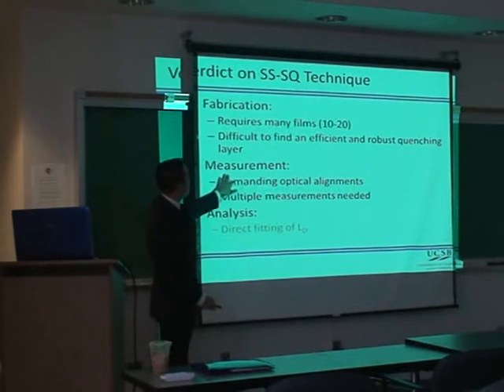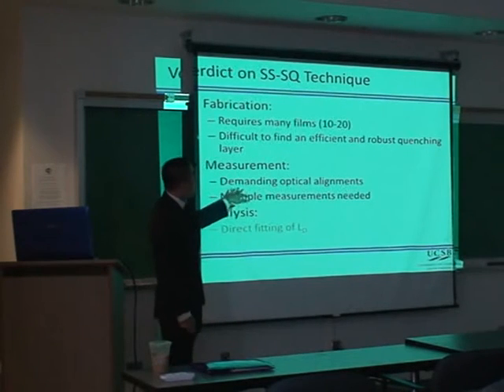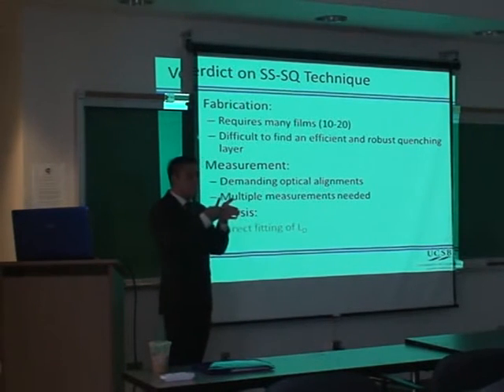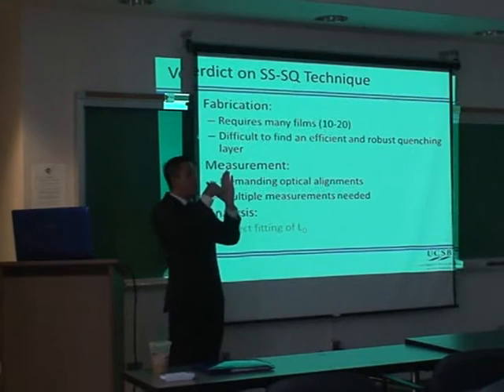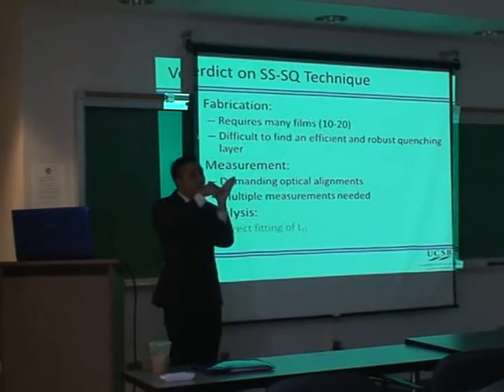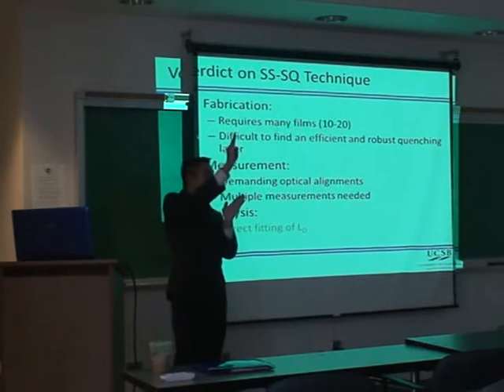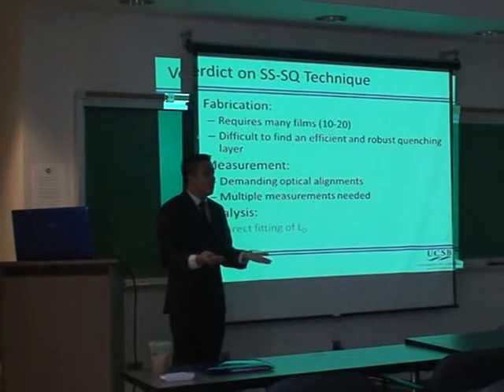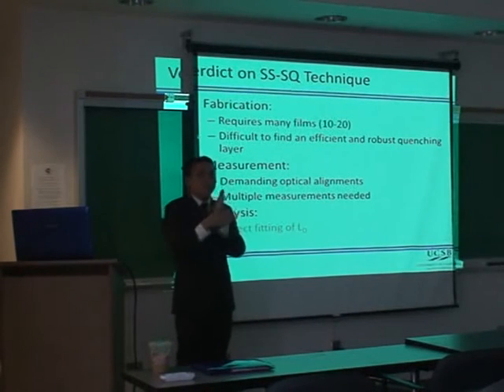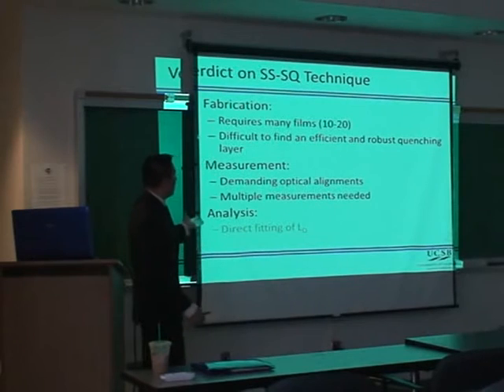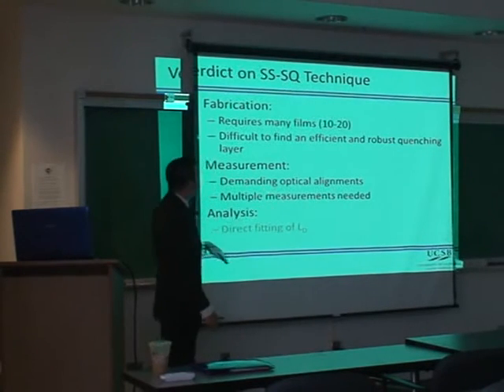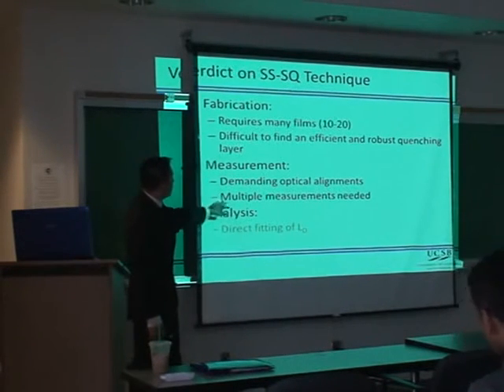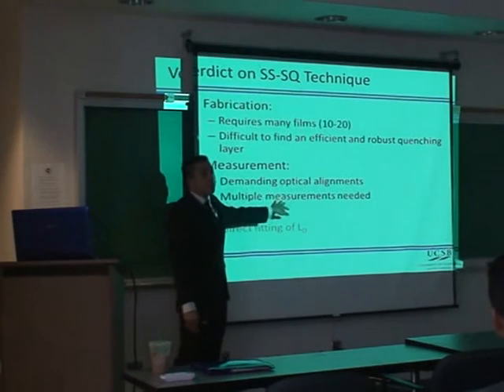In terms of measurement, it's actually quite demanding too. What I didn't mention is that when we measure these films, you can imagine that we have to hit these films very normal. If we were to hit them at an angle, some of the light will get reflected, and that would appear as quenching. So it's very important that we hit all these films very normally, and that requires a lot of accurate optical alignments.